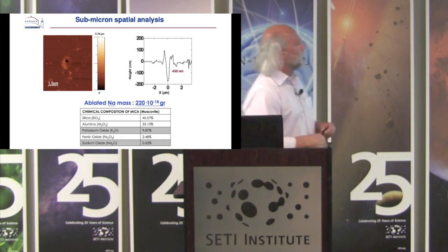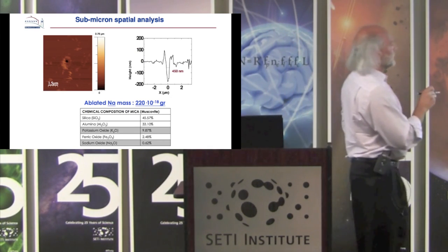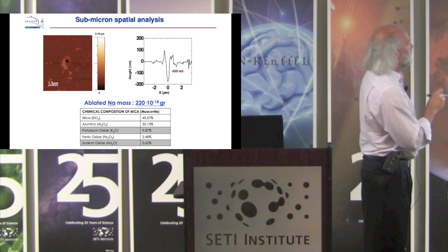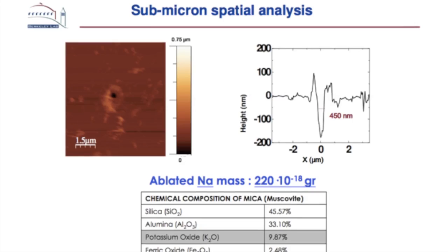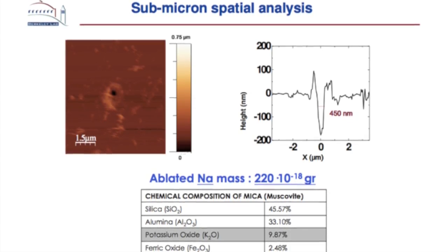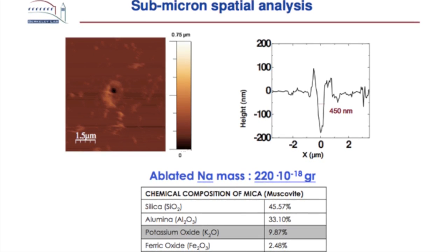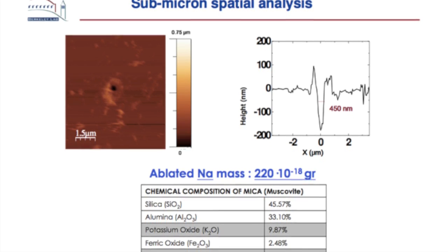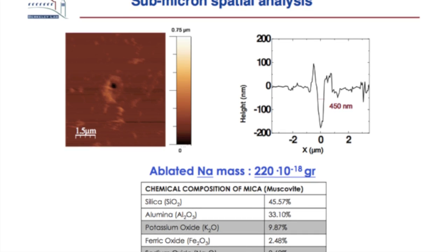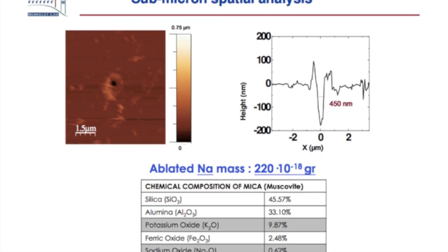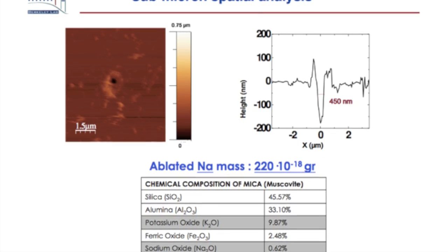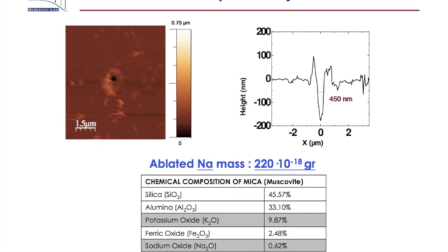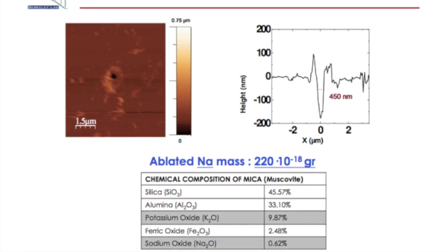Okay, so here's the analytical chemistry. If you look at the sodium concentration in that sample, we basically ablated about 220 attograms of material, and we're seeing a signal. Single laser shot, we're doing attogram detection limits. And that's assuming all of that sodium mass was excited to emission, which I know it's not.